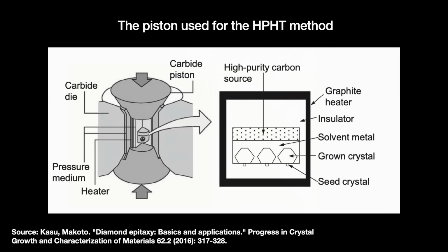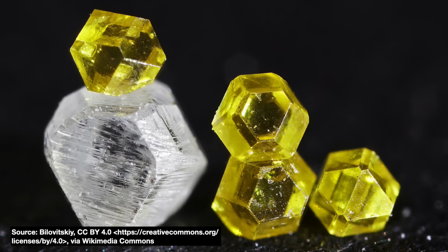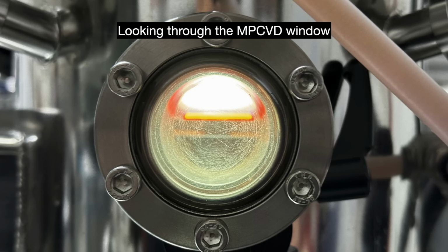HPHT-produced diamond crystals have few lattice defects, which is good, but there are three problems. The first being that the diamonds are too small to do much with. And two, HPHT introduces unwanted impurities into the diamond from its surroundings, like boron, cobalt, and nitrogen. Ergo, why so many HPHT diamonds are yellow. They have within them 10 to 100 parts per million nitrogen impurities. The third issue is that the HPHT method itself is expensive and high maintenance.